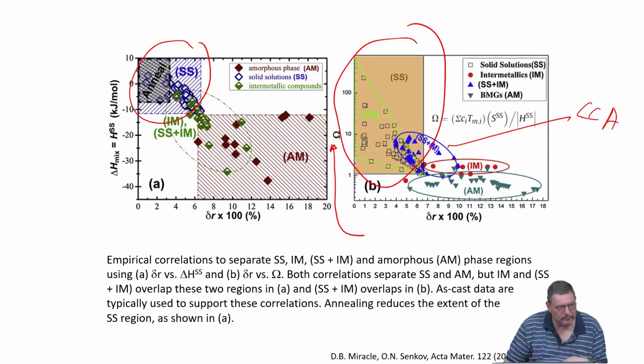Then suppose during printing, during solidification, cracks will form. Yes, that is also a possibility. That is always a possibility. So then you have to basically change processing conditions. It's not related to the thermodynamics, it's just about intrinsic strains. So you maybe have to think about how your cooling method is affecting the crack formation, whether you need some stirring, things like that, or whether you need to do maybe Bridgman solidification to avoid that, to get closer to equilibrium configurations, which avoids building up stresses so much.